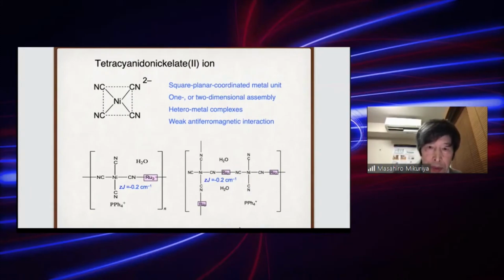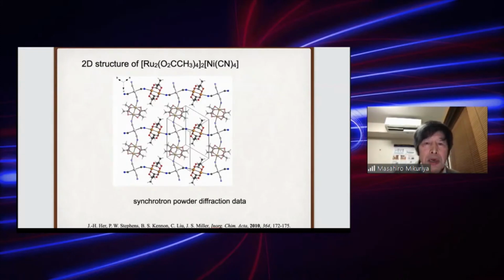But for this system, Miller's group reported synchrotron powder diffraction data and found this kind of assembly structure. So when I saw this report, I was disappointed that we could not obtain single crystal for our system. But on the other hand, this encouraged us to continue our study.